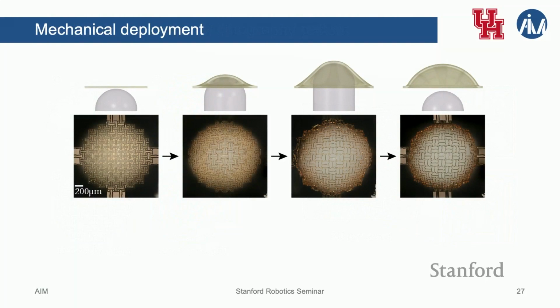And now we can do this. So how do we deploy this particular geometry? As you said, we take an indenter and we just keep on pushing. We push it way past its second equilibrium, and then we let go of the indenter, and it returns to that prescribed shape. So that's the 4-stage process. We start from flat, we push, and we push past its second equilibrium. So each unit cell has extended beyond the lambda that we assign, and then we let go of the indenter, so it goes back to that shape that we decided.